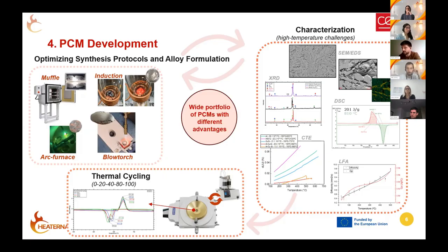Once the ideal properties of this alloy are confirmed, we move on to a critical test, the thermal cycling of the alloy around the phase change temperature of the PCM. And I say that this is a key test because it evaluates the evolution of the thermal properties over 100 thermal cycles in the presence of air.